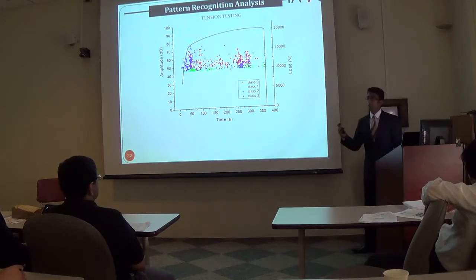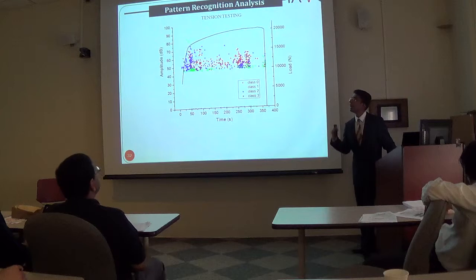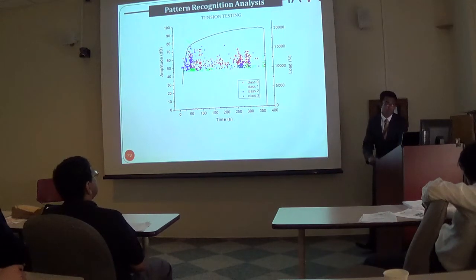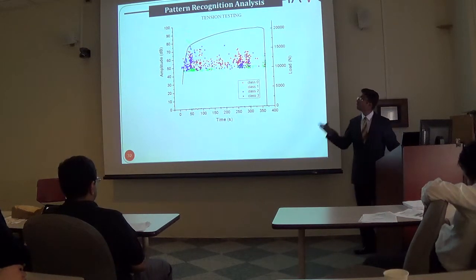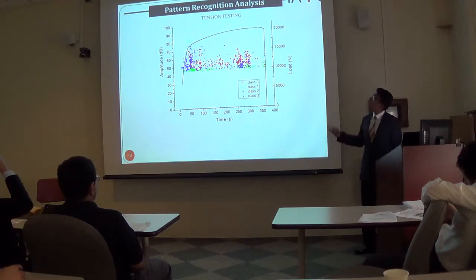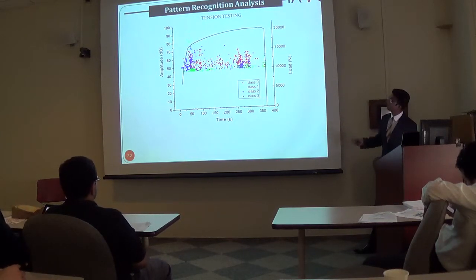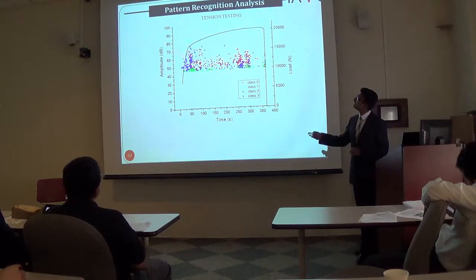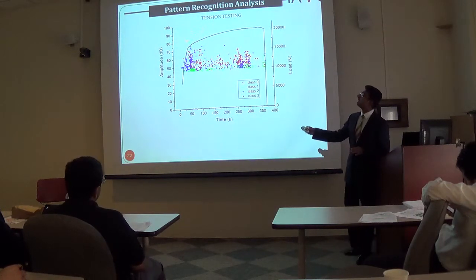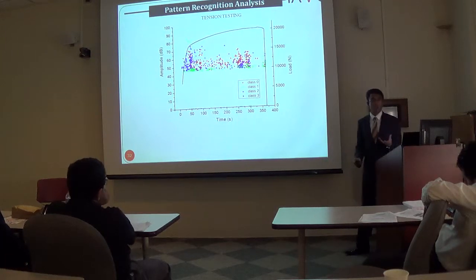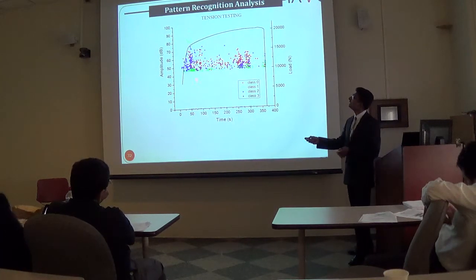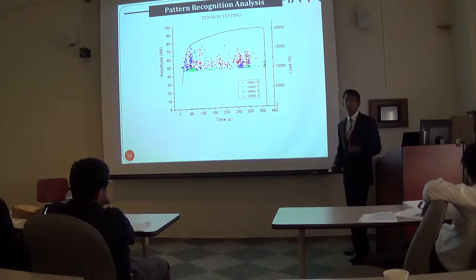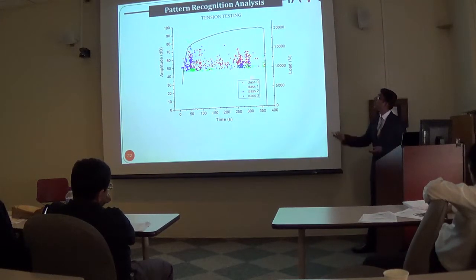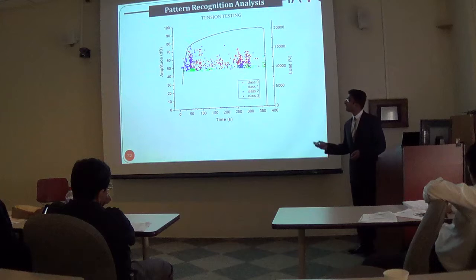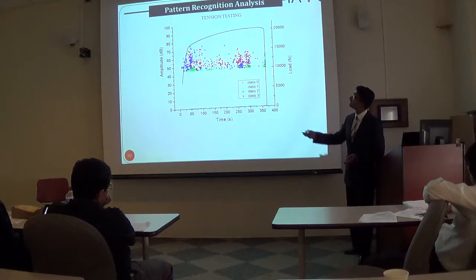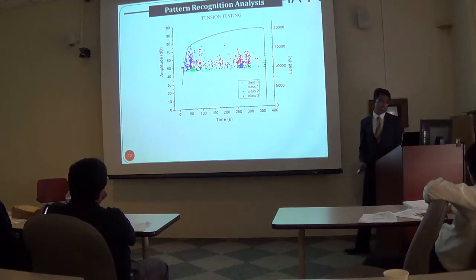Now, in order to put these classes into perspective and understand exactly how these different classes activate in the material, the classes were correlated to the applied loading condition as you see here. And you can see how the different classes are activated at specific load intervals. So initially at the yielding, you can see that the green class, which is the class 1, is seen to be dominant, while prior to yielding, you can see the blue class, which is class 2, was seen to be more dominant and picks up. While the class 3 signal, which is the red class, is seen to significantly increase post-yielding and then dominate the post-yielding behavior.